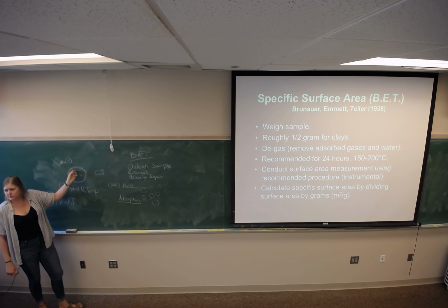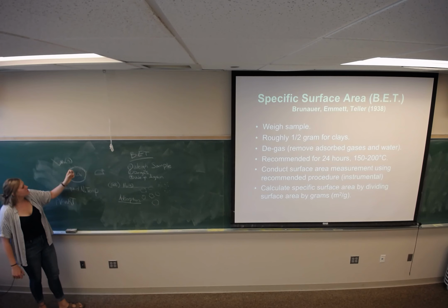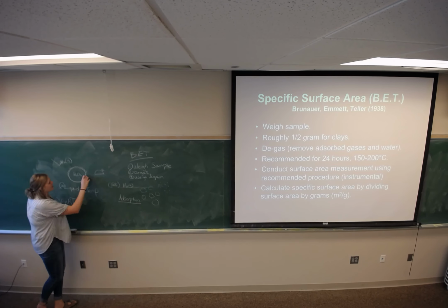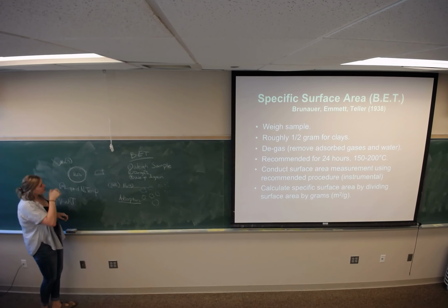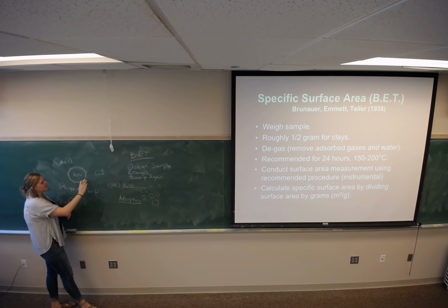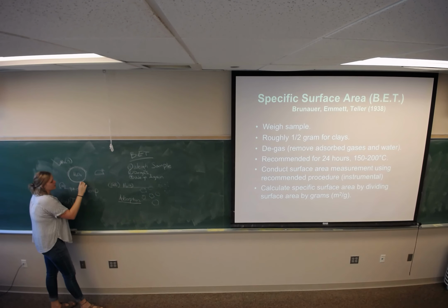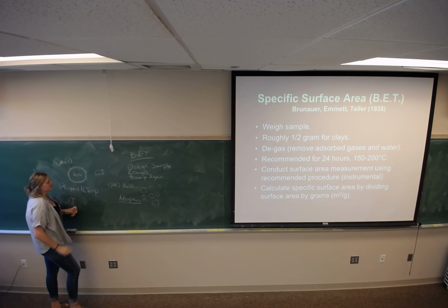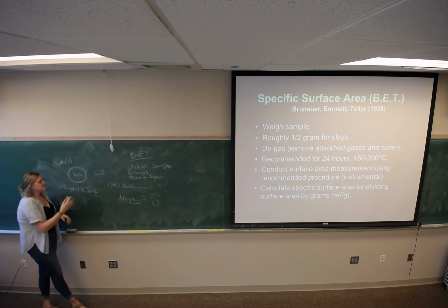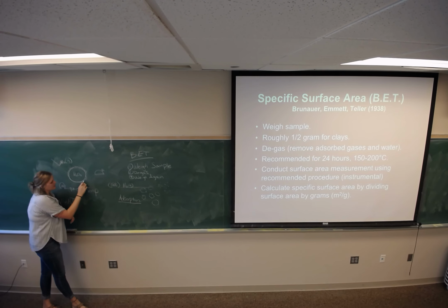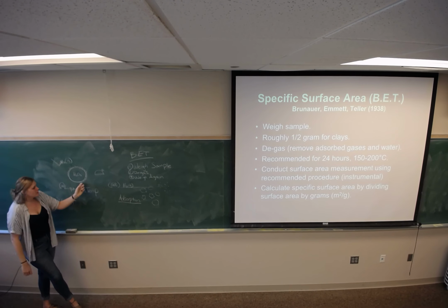Make general sense? All right, so the key thing about the BET that Dr. Carty always stresses is that this method corrects for multi-layer coverage on this powder. That's something that always shows up on some of his exams and homework questions. So let's say you have molecules that are not perfectly spaced and you still have some open surface. What ends up happening is you're going to get nitrogen molecules that might not be stacked exactly in one layer. So the BET method corrects for this, which is nice.